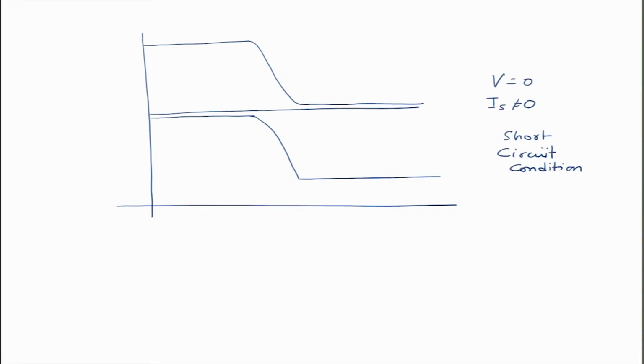condition, all right. So in this short circuit condition, since you have of course increased the hole concentration, so hole concentration will obviously be increased. So there is certain P_P, but you also have a large increase in N_P, which means the quasi Fermi level that corresponds to electrons will increase here. So this is E_FN. If I just plot it like this, E_FN will be something like that. Similarly, you will have quasi Fermi level for holes. So this is E_FP.